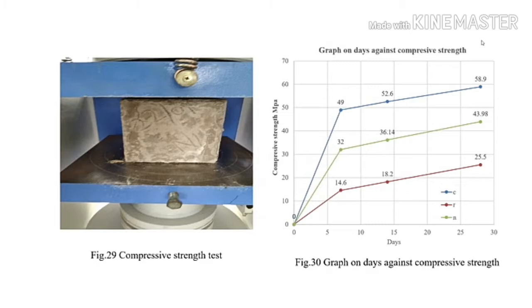Figure 29 shows an example of compressive strength testing. The graph of compressive strength was plotted. The specimen C represents conventional design, which was found out to be 58.9 megapascal. The specimen R shows an example of the concrete with 60% of fly ash and waste materials, which was found out to be 25.5 megapascal. The specimen N represents the concrete with waste materials, 60% of fly ash, as well as nano-silica and cactus gel, which was found out to be 43.98 megapascal.